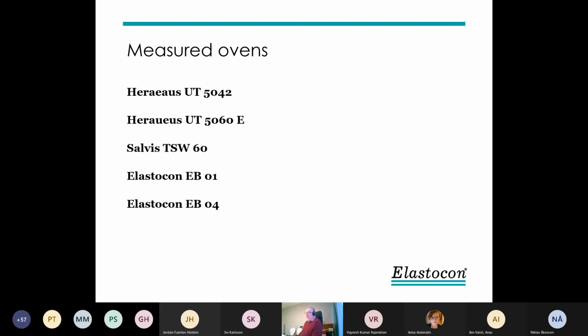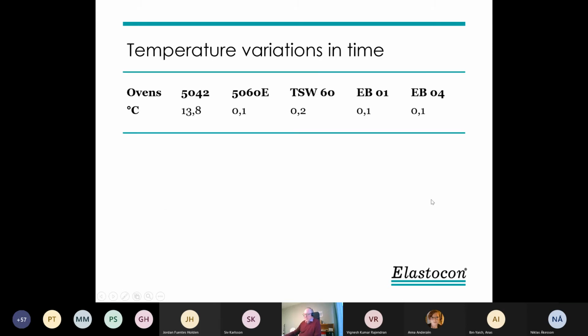The ovens we measured were these ovens, 2 of our own ovens and the ovens which were very much used in the rubber industry in Sweden at that time. We looked at the temperature variations in time, and they were all good except one oven, but that oven happened to be an old oven with a bimetal thermostat and not an electronic thermostat. So as long as we have some electronic thermostat, they can keep a constant temperature quite well.